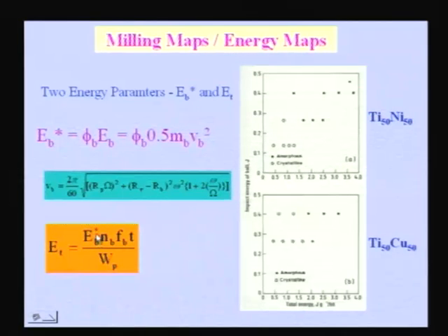Total energy of the ball is nothing but the impact energy of the ball, number of balls, the frequency of impacts, and time of milling. All of them will come in the numerator, and the weight of the powder comes into the denominator. That means if you put a large amount of powder, then the total energy transferred to each powder particle obviously decreases, because there are too many particles to receive the impacts. If you have fewer powder particles, then each particle receives more number of impacts. So as a result, the total energy transferred to the powder particle is more.